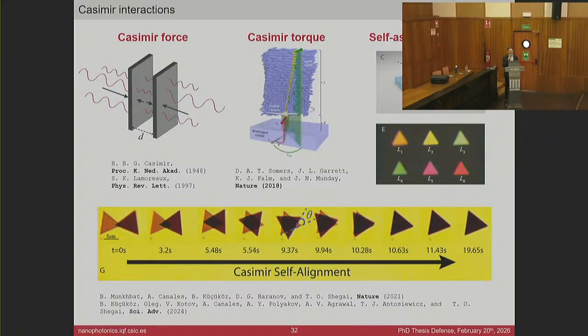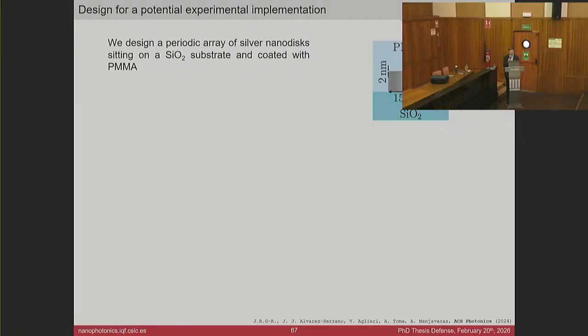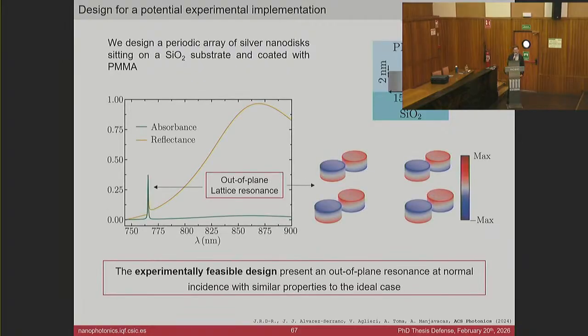I have actually at some point made some calculations for the case of the out-of-plane lattice resonance. Seeing this was kind of a strange configuration, we wanted to check if it survives making a different kind of nanostructures, like nanodiscs that are more simple to produce in experiments, and also introducing conventional substrates and superstrate, in this case silicon oxide and PMMA. And you could see that the resonance survived with really nice properties.